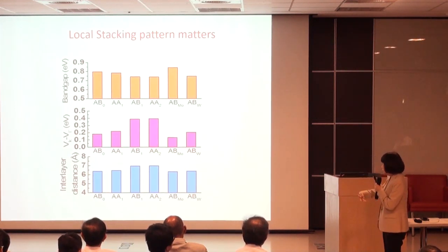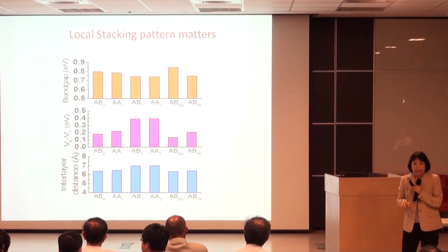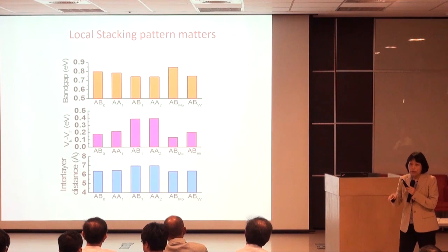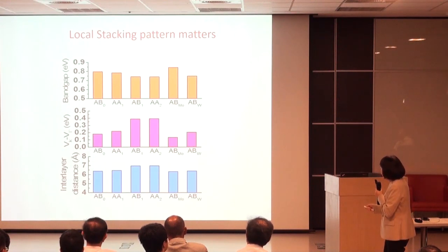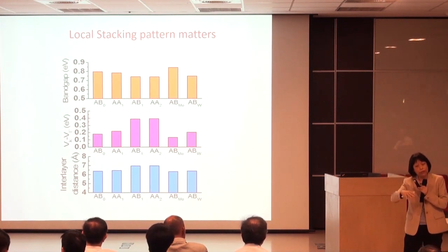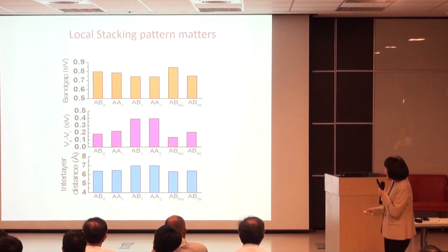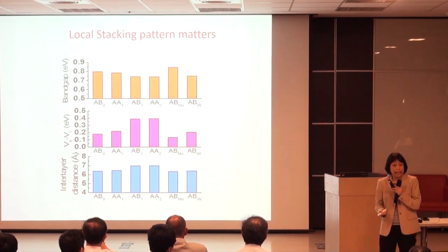And we have a region which is large enough so that the local picture could be measured by local probes like STM or scanning tunneling spectroscopy. Okay? So with the interlayer separation, it's going to have a variation of about 0.5 or so angstrom. So the whole thing will be buckled. Once that happens, the local band gap is going to vary by the order of a few tenths of an eV.